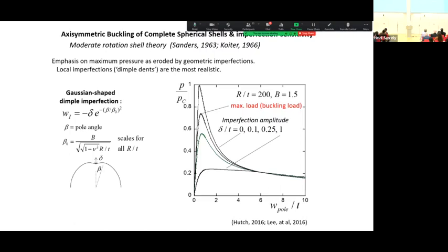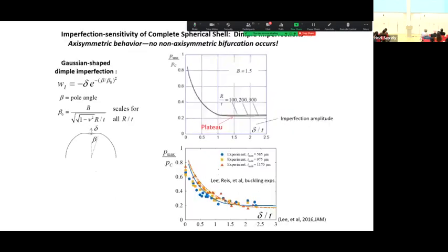So, you know, for a thin shell, you probably wouldn't even recognize by eye a 1 thickness imperfection. You certainly wouldn't recognize one that's a 1/10 or a 1/4. But notice that here's the quarter right here. Notice that a quarter-thickness imperfection reduces the buckling load to almost 50%. And when they're down on the order of 1 thickness, they're down to that 0.2 ratio.